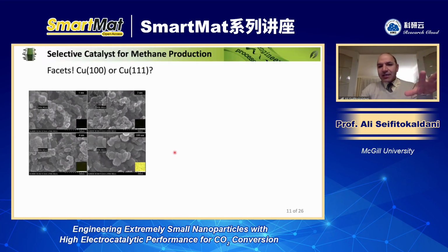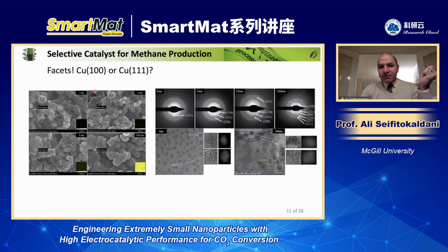So after synthesizing that, we were interested to know if we have the 111 facet or the 100 facet, what facet do we have? Our TEM and SAED showed, as we were expecting from the DFT computation, that for small particles such as 1 nanometer, you only see 111 facets. While as the particle size increases to 100 nanometer, for example, then not only do you have the 111 facet, but you also have the 200 or 100 facet.